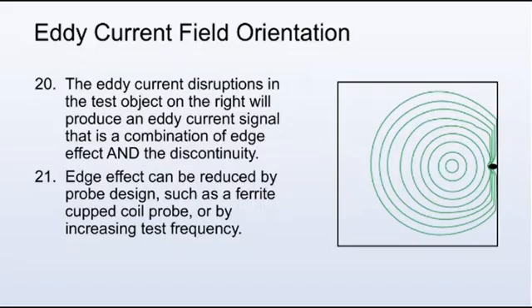Edge effect can be reduced by probe design, such as a ferrite cupped coil probe, or by increasing test frequency.